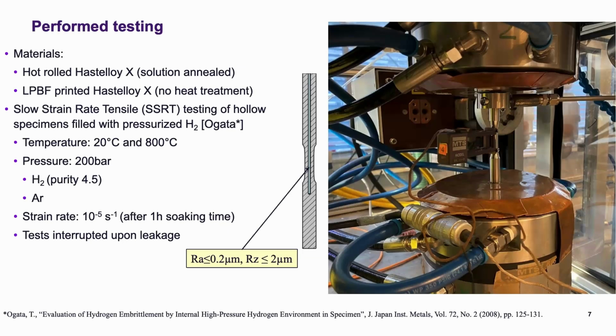So that is critical from my perspective to be able to get close to the operating conditions. We do need to cycle both temperature and strain. And I see this as an important complement to the autoclave testing methods where we are usually confined to isothermal testing conditions. And at least for the foreseeable future, we're also limited to lower temperatures than 800 degrees, as in this case.